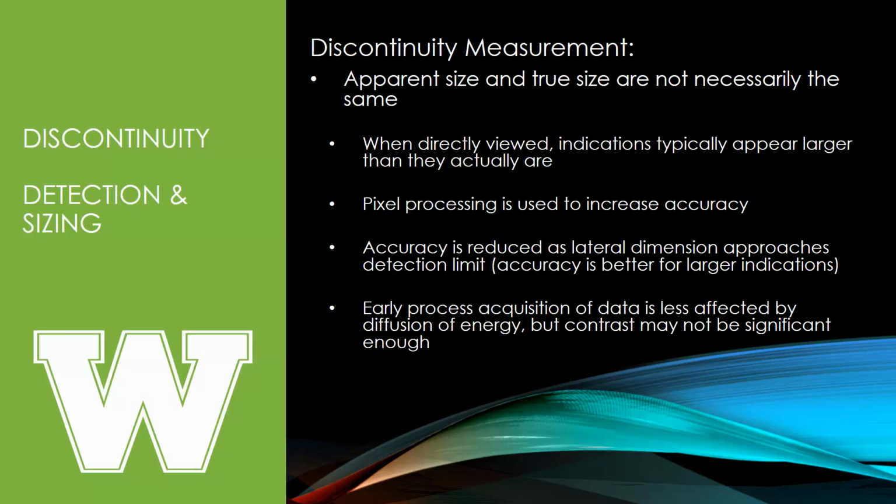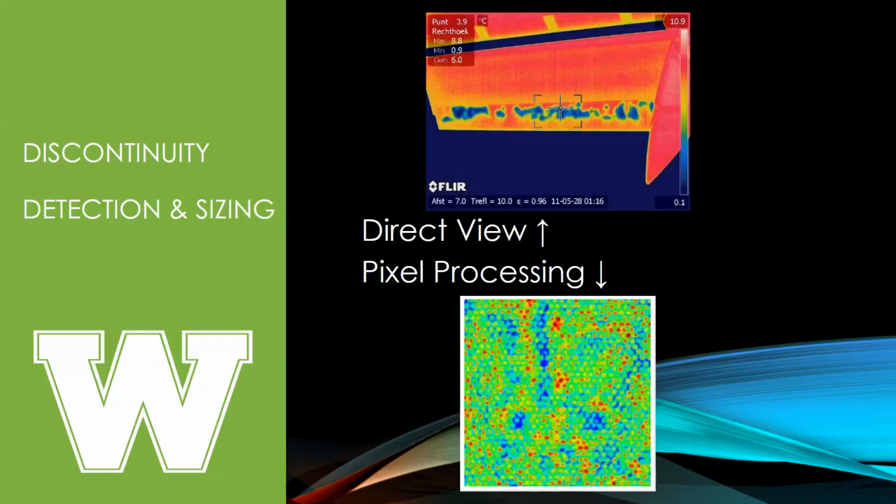Right? Areas of skin, of bare skin, just skin, will cool off faster than areas where skin has like ribs and stringers behind it, right? Because there's more mass and material there that hangs on to that heat energy. So if it's cooling. So where you see it is something like this.